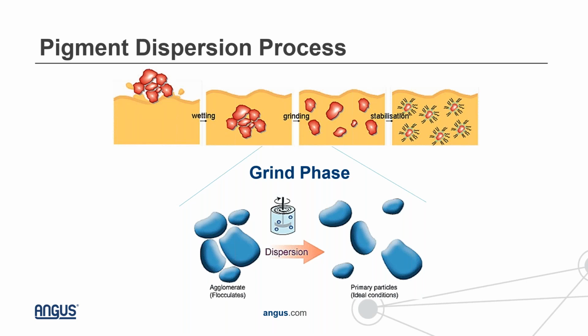So the pigment dispersion process is something that I'm sure all of you on the call are quite familiar with. But essentially what you're trying to do is take a pigment that's usually supplied as a solid powder in aggregate or agglomerate form, and you need to get that into water. So you first need to wet out those pigment surfaces, and then you apply a lot of energy through grinding. What this does is break down the aggregates into individual primary particles.